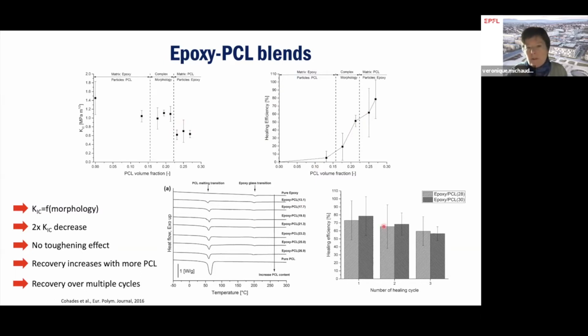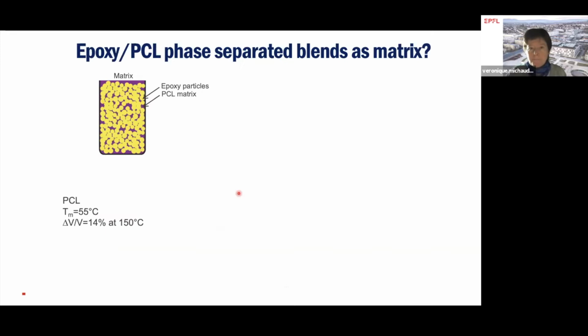And we found that it works, and you get a good healing efficiency after several healing cycles. And depending on the blend, of course, you check that actually it's really a phase-separated blend where the PCL is still obvious in the DSC traces, as well as the epoxy glass transition. Note that the epoxy glass transition is high enough so that thanks to this connected epoxy morphology, when you heat up the material to 150 degrees, you don't lose all mechanical strength because you still have this network of epoxy to keep it. So then we considered if we could use it as a matrix.